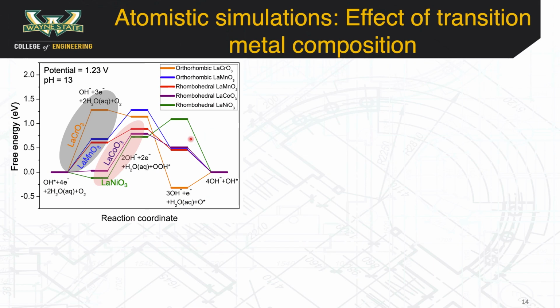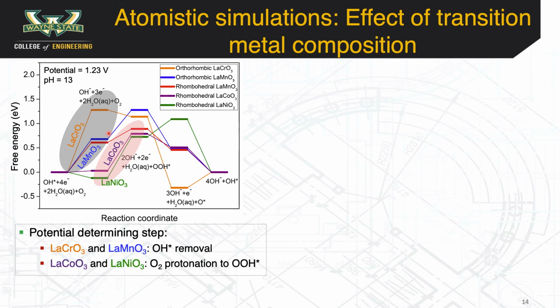Similar to earlier, we benchmark our theoretical calculations using a free energy diagram. What is observed is oxides to the left of Mn, including Mn, are limited by strong adsorption of oxygenated intermediates, leading to OH removal, generating a clean site being the potential determining step. While oxides to the right of Mn, including cobalt and nickel, are limited by weak adsorption of oxygenated intermediates, thus making O2 protonation to OOH the potential determining step on these oxides.